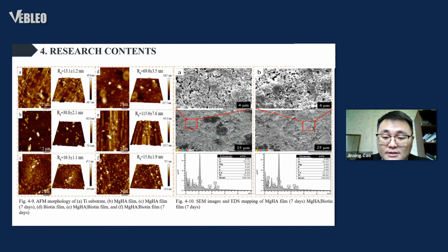Similarly, those pores can be clearly observed in Figure 4-10, which are formed by the corrosion degradation of magnesium in the films in contact with simulated body fluid.